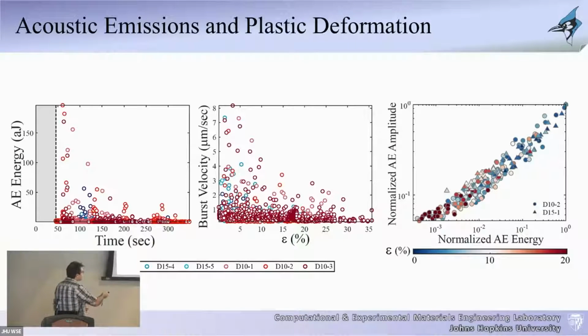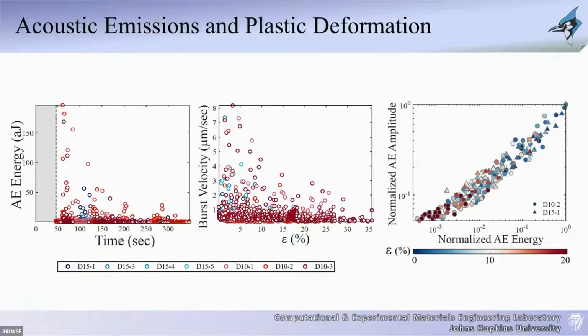versus time. This is what you would get from the load displacement. You can calculate the burst velocity versus strain. And you can look at the normalized acoustic emission amplitude versus the acoustic emission energy. Now, the intriguing results, again, there's a lot of data here that I'm not going to go through in too much detail, but one of the very intriguing things is when you look at this curve here, in this case, it's color-coded according to the strain level. You would notice that the blues are on top here and the reds are down here.